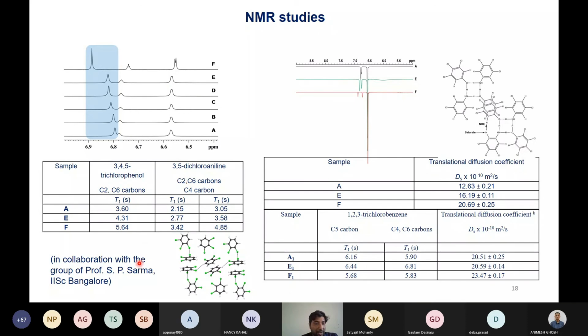In addition to that, Professor Sarma's group performed some advanced NMR techniques, including translational diffusion coefficients and T1 experiments. So both of these tell us that the T1 constant increases when molecular size decreases, because of the rotational freedom it offers. And the translational diffusion coefficient is also inversely proportional to the radius of the molecule. So if you go through the trend of A, E, F, you'll see that in both these cases, these things are maintained, that at highest dilution, that is at F, the stacking is breaking, but the hydrogen bonding is still intact. And for a benchmark, we used trichlorophenol also, just to see that our results are consistent.